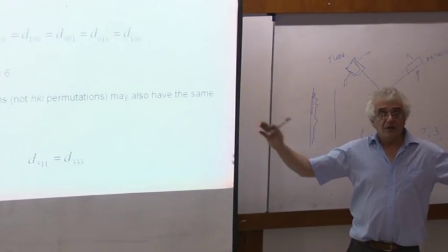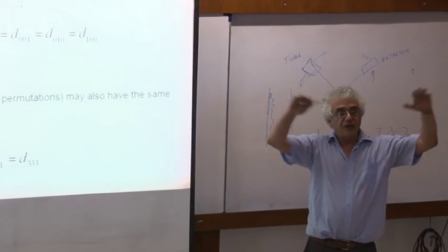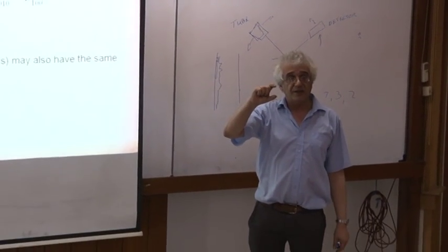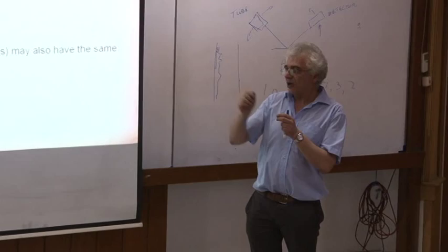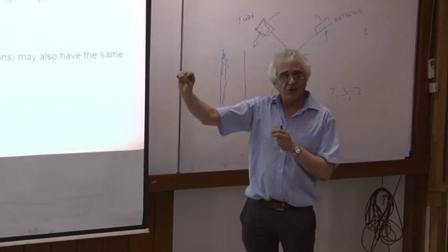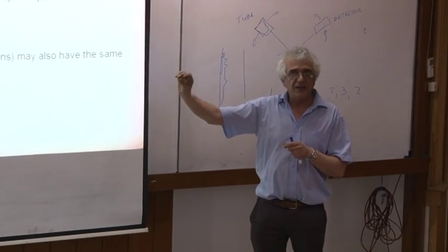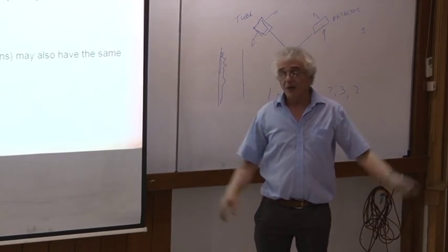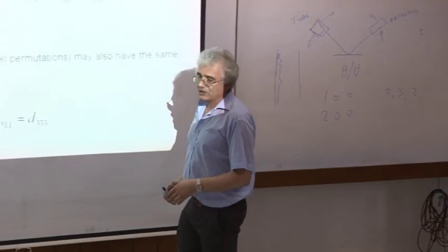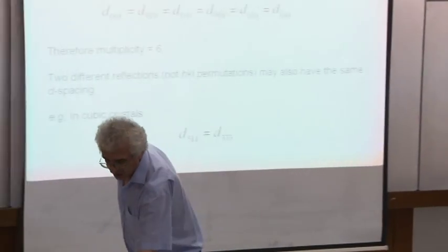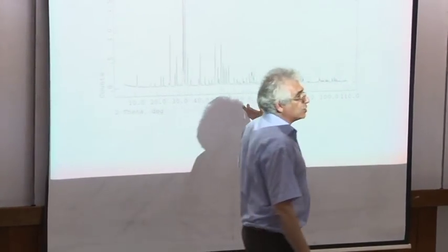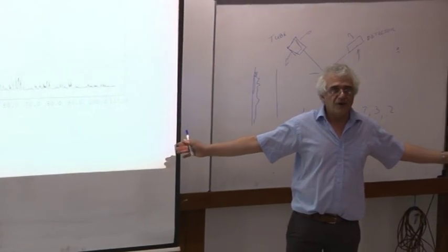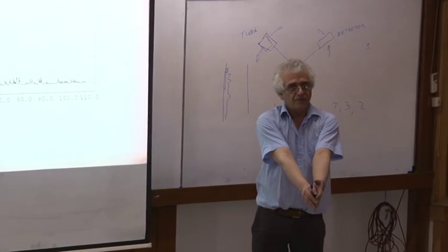Now, that's because in 3-dimensional reciprocal space, if I've got a single crystal like this, I can actually go to that reflection and measure that 100 distinctly as opposed to -100. It's in a different position. Here, remember what we're seeing in our diffraction pattern. Our diffraction pattern is one-dimensional here. So we've reduced our three-dimensional diffraction pattern to one dimension.